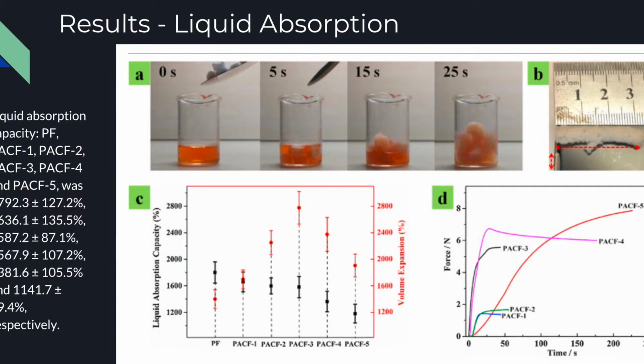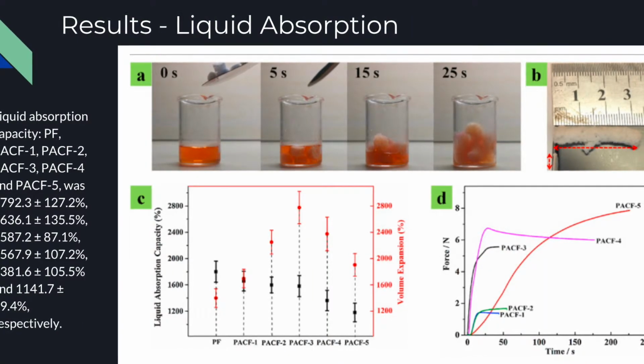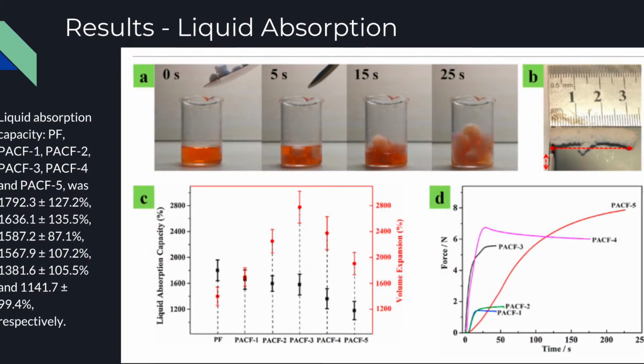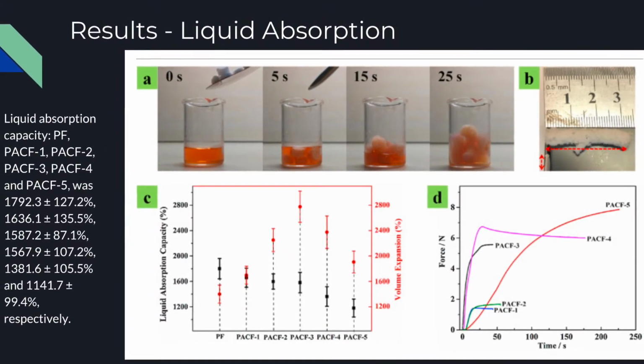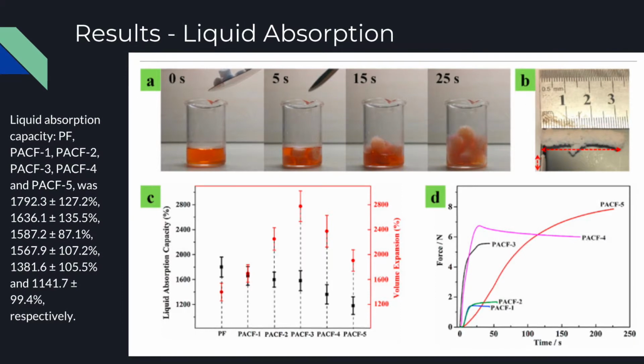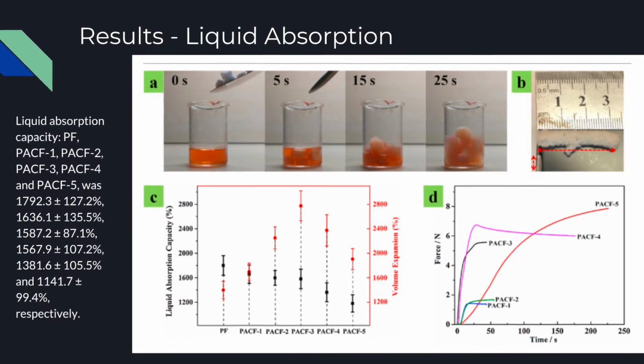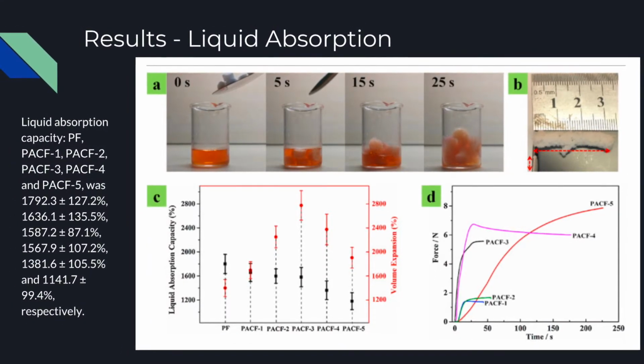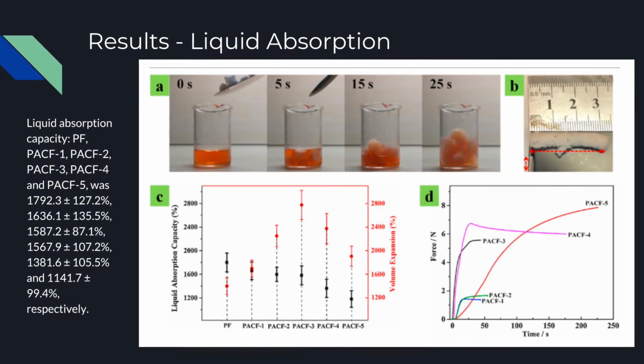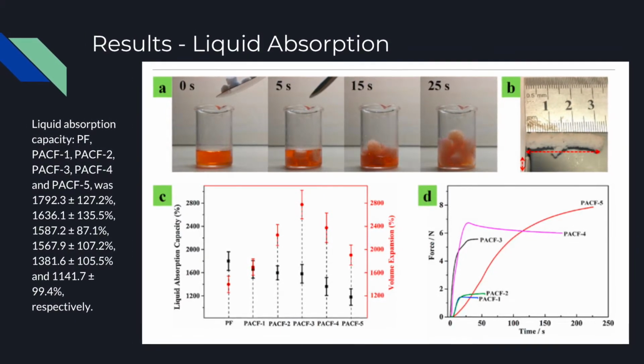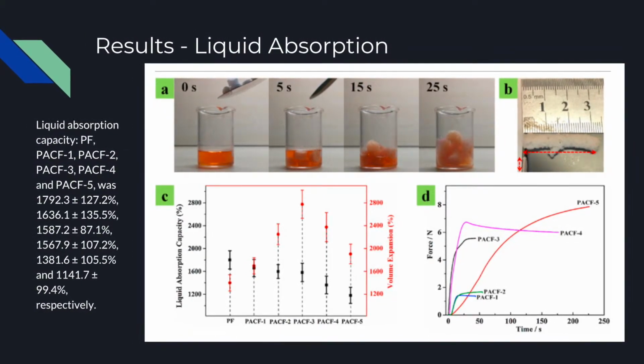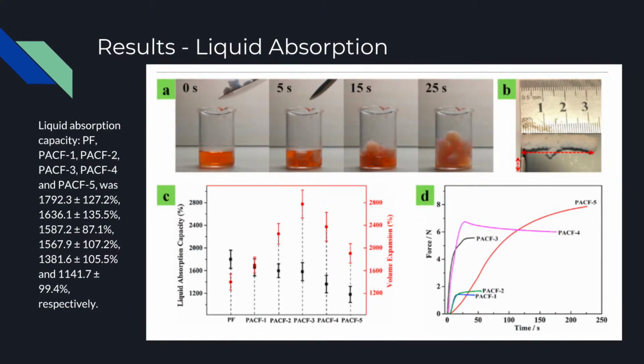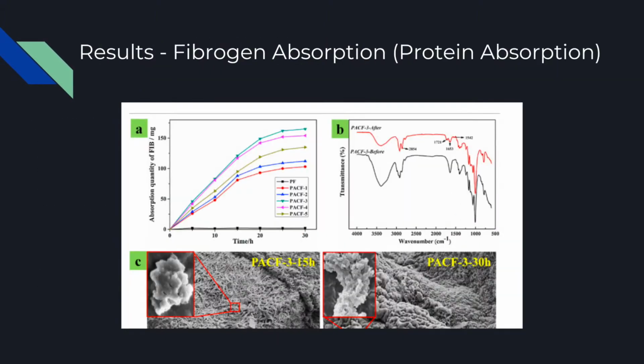For liquid absorption, 15 milliliters of liquid could be fully absorbed by the PACF within 20 seconds, the capacity ranging from 1,792% to 1,141%. Volume expansion rate average was 2,000% in figure C, and expansion force ranged from 1.5 newtons to 8 newtons, which is sufficient radial force to apply pressure to wounds from within.